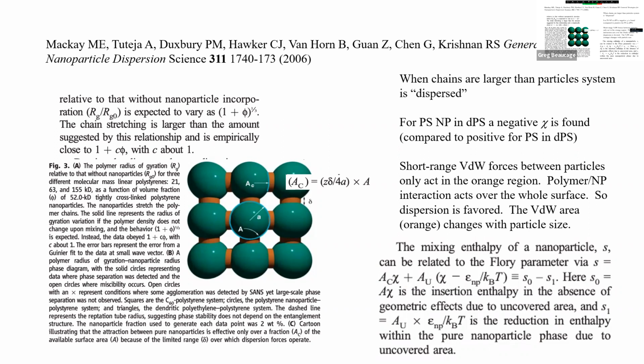Right? So basically, it's a short range interaction. You have to be close to this thing. So 1/r² actually relies on a rapid decay. Because of that, if you have spherical particles, they have a region where they're going to interact that's just over this kind of strut thing here. So if you have large particles, there's not going to be much of that area. If you have small particles, there's more of that area. Then you get a particle size dependence to the reason that these things would attract and not attract. And also, in that region, they're going to distort the polymer more. So somehow he has a scheme where he can explain this using thermodynamics. It seems to be somewhat contrived, but basically that's a 1,200 citation kind of idea.